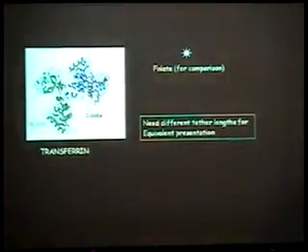An issue that we had to deal with was if we were looking at multiple ligands on our liposome surface, and for example, we were looking at transferrin and folate, it turns out that they are very different in size. Here's a cartoon of the folate molecule with respect to the transferrin molecule. They're very, very different in size. And in order to present both these ligands to the cell surface at exactly the same place, we need to put these things on relatively short tethers and the folates on very long tethers.